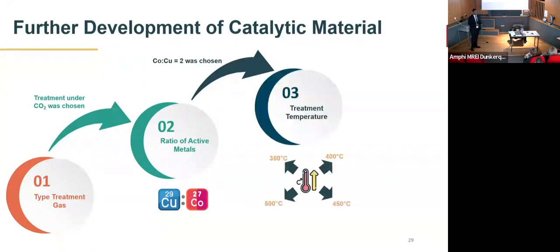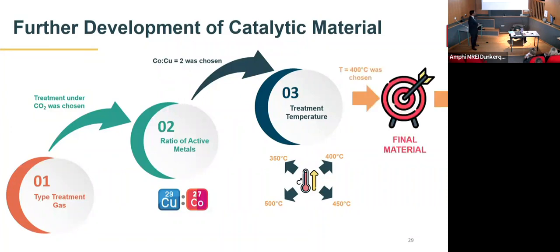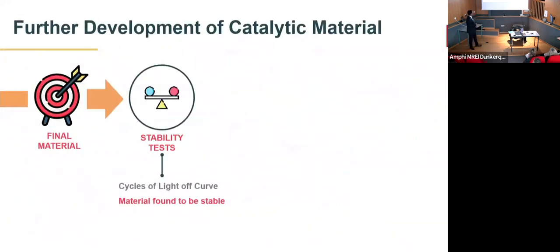The next step of the material development was to investigate the influence of treatment temperature on the catalytic activity. In this case, we used treatment temperatures between 350 degrees Celsius and 500 degrees Celsius, and we compared the catalytic activity of the mixed oxide obtained after the treatment at these different temperatures. We saw that the 400 degrees Celsius sample showed us the optimum catalytic activity and therefore was chosen as our final material. This material was then further used to study for the stability test.